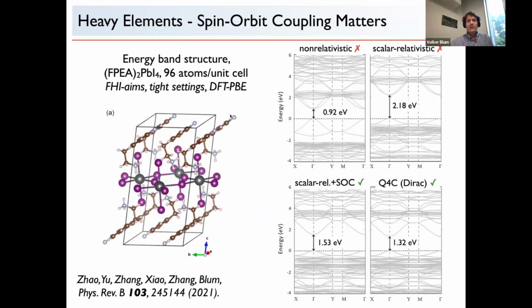I mentioned that spin-orbit coupling matters. So this is the picture that we have. We could in principle do non-relativistic calculations, right? And this is the energy band structure that we get. If you incorporate scalar relativity, which is critical for anything, I think, in chemistry, also lighter elements, then you see that the energy bands shift, but they don't change really in character. And if you incorporate spin-orbit coupling finally, then you see that something qualitatively changes. These two levels here split as they should, and the energy band gap also changes. And so the conduction bands in particular are heavily affected.